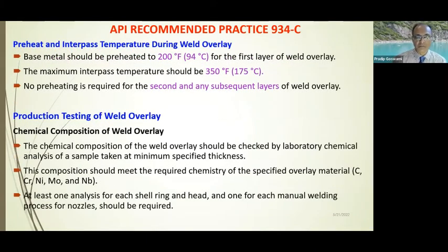And continuing on the manufacturing process, what you can see is that during the weld overlay, the base metal shall be preheated to 94 degrees centigrade for the first layer of the weld overlay. That is very important. You do not need, as a matter of fact, any preheat for the subsequent layers, but one has to control the maximum interpass temperature generally to control any kind of sensitization issue. In order to achieve that, the maximum interpass temperature generally should be controlled below 175 degrees C. And as I mentioned earlier, no preheating is required for the second and any subsequent layers of weld overlay.